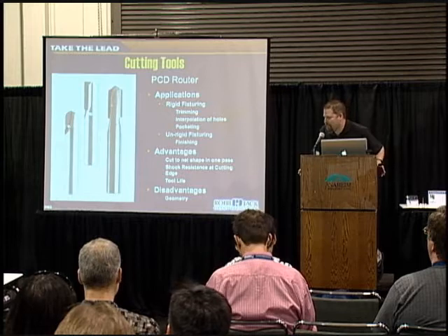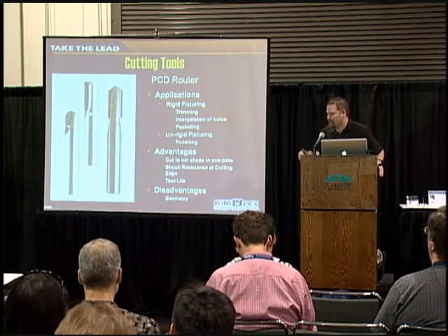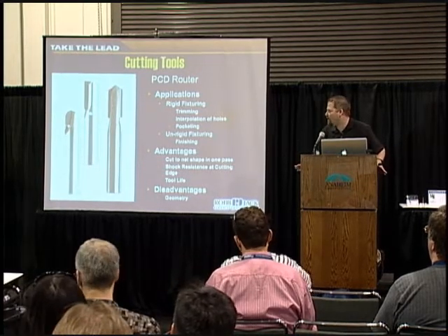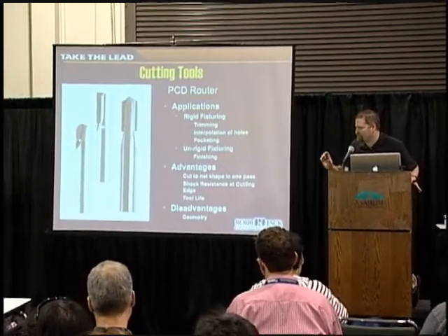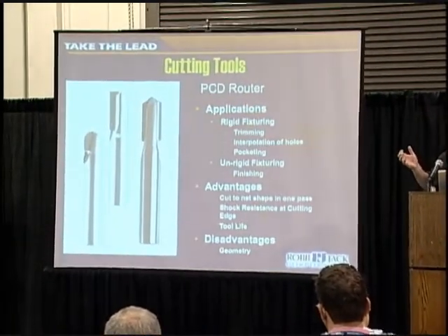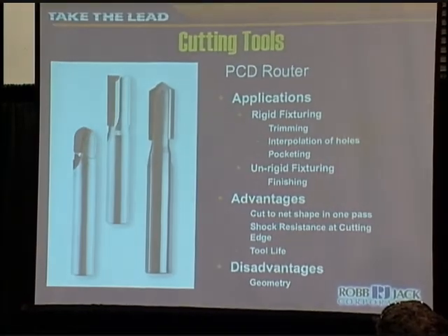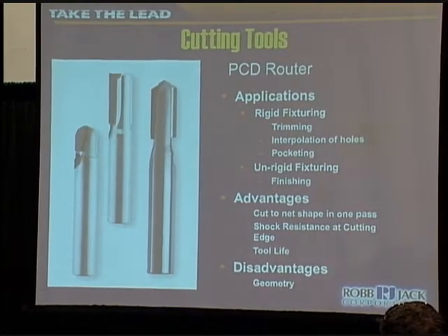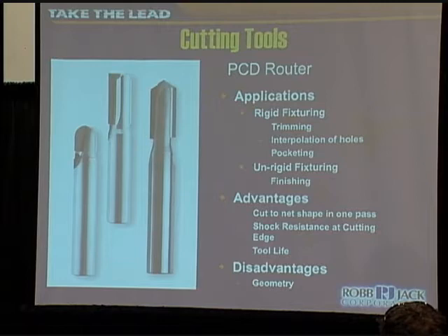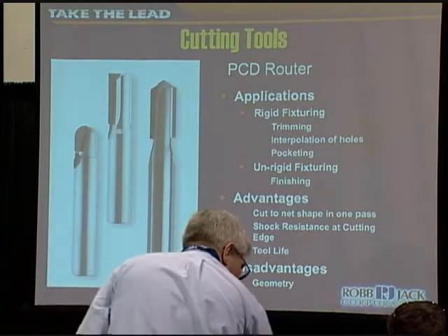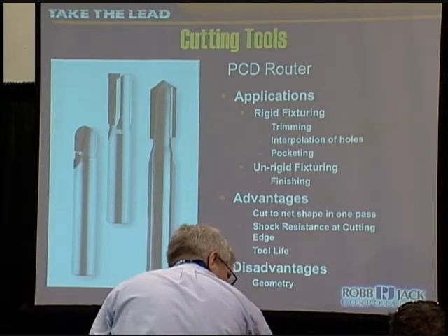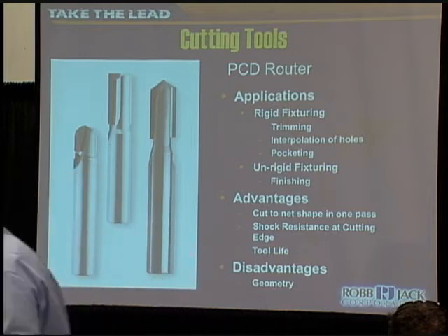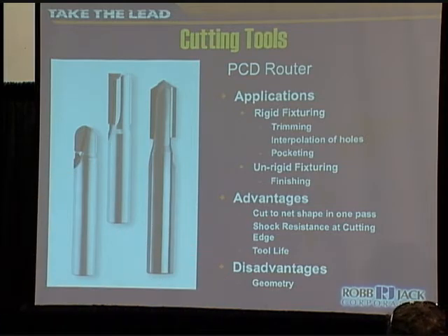So when you get to the PCD router, which is probably the most common tool used when you're trimming out parts, it's usually straight flute so that there's no shear to it, so you're not putting up force or down force on the part. It helps get rid of those fibers from pushing up out of the way because it's kind of pinched between the material itself and shears off those fibers. It's really good for trimming.